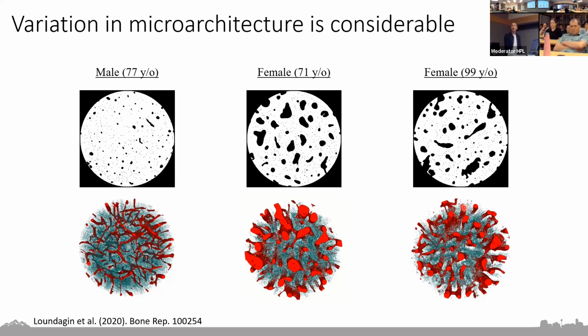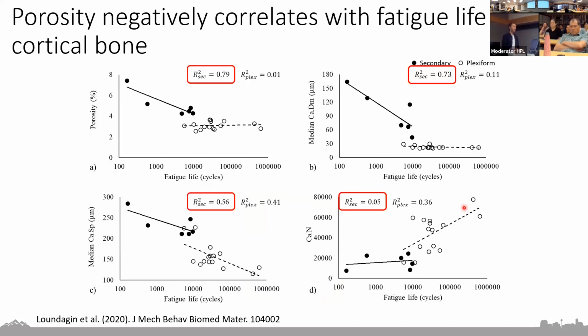But there hasn't really been much work looking in equine subchondral bone at how this variation in microarchitecture can influence fatigue life. But there has been a little bit of work looking at human and bovine bone. A lot of this work has demonstrated that a large majority of this scatter can be attributed to differences in microarchitecture. And there have been a few studies that have found porosity to really strongly negatively correlate with the fatigue life of cortical bone. In this plot here in the top left, we just focus on those filled-in black dots, which is secondary bone. You see there was a pretty strong relationship between porosity and the number of cycles to failure.